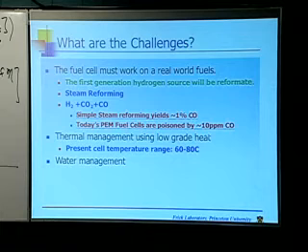But if I now want to think about, I'm going to stop at the local gas station and tell them to fill it up with real live gas with hydrogen, I don't really want to pay for reagent grade hydrogen that has less than 10 parts per million of CO in it. I'll never be able to afford that. Okay? So we need to generate a fuel cell that maybe doesn't tolerate 1% CO, but does better than 10 parts per million. To the extent I can step away from this, the hydrogen just gets cheaper. Okay. So that is really the big ticket issue.